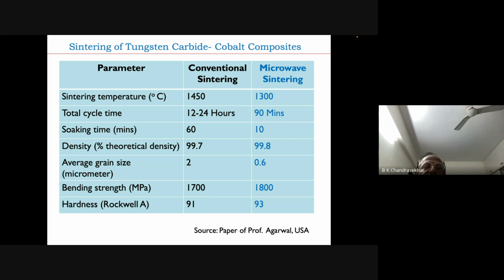The melting point of tungsten carbide is very high, I don't know, 2000 degrees or more. So normally it is extremely difficult to sinter that material by powder metallurgy technique. So what people do is they put a little bit of cobalt into the tungsten carbide composition, and this cobalt melts and forms an interface layer.